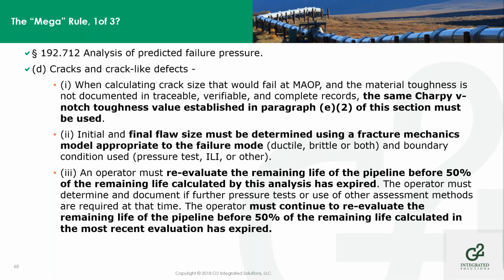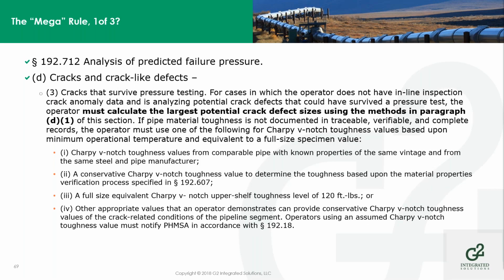And the operator must reevaluate the remaining life of the pipeline before 50% of the remaining life calculated by this analysis has expired. So you must determine and document if further pressure tests must be done, and you must continue to reevaluate the remaining life of the pipeline before 50% of the remaining life calculated in the most recent evaluation has expired. In other words, you've got to keep looking at it. It's not a one-and-done event. And you have to calculate the largest potential crack size defect using the methods in paragraph D1. And following these Charpy V-notch toughness values based upon minimum operational temperatures of a full-size specimen. And then of course, the description here for the toughness values, comparable pipe, determine the toughness based on material properties, so on and so forth.